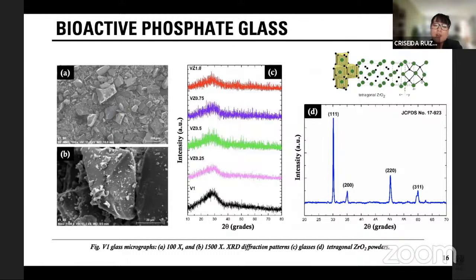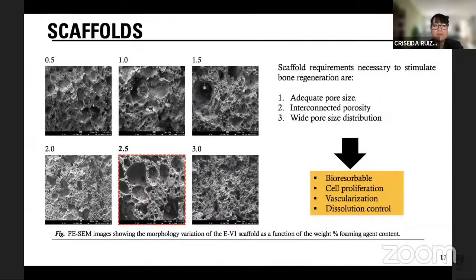This slide shows part of the article results, illustrating the glass's amorphousness and the irregular glass powder's morphology. These images were obtained by a scanning electron microscope. The last image shows the diffraction pattern with the tetragonal crystalline structure. The zirconia acts as a nucleating agent helping the glass crystallization. Then the bioactive glass powders were obtained and mixed with beta-tricalcium phosphate powders in variable amounts with different reagent ratios until obtaining a scaffold with a wide pore size distribution.